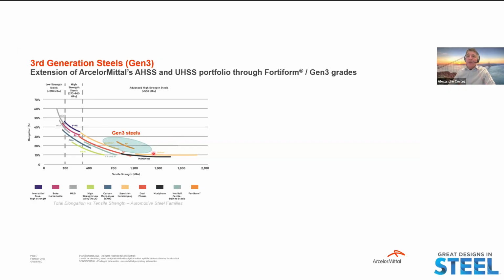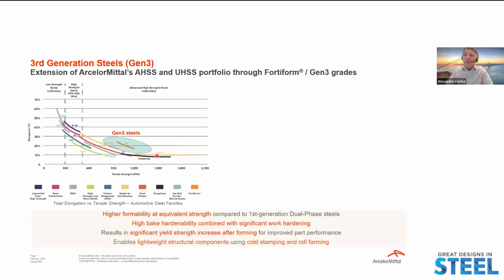Our Gen 3 product is located here in this portion of the graph, and it's bringing higher formability at equivalent strength compared with the first gen of DP grades, and high bake hardenability combined with significant work hardening. It results in a significant yield strength increase after forming and improved part performance, enabling lightweight structural components using cold stamping and the roll forming process.